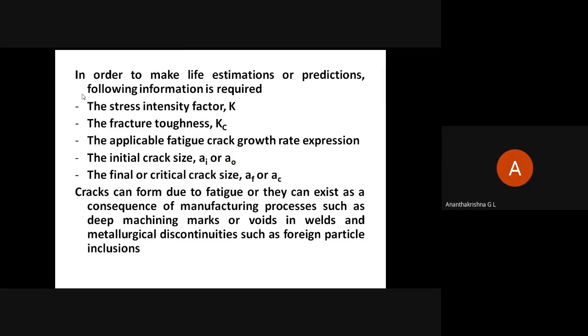Dhanush, read all the five one after the other, right from the start. In order to make life estimations or predictions, following information is required. The stress intensity factor K, the fracture toughness Kc, the applicable fatigue crack growth rate expression, the initial crack size Ai or A naught, the final or critical crack size Af or Ac.